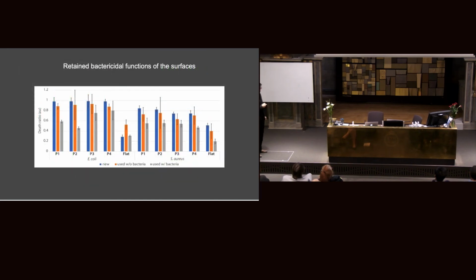After these bactericidal tests, we also examined the retained functions of the surfaces. This was done by comparing a newly fabricated surface with a used surface, where we put the surface into the bacterial solution, took it out, washed the bacteria off, and used it again. Used with bacteria means we take the surface, incubate it with bacteria, take it out, and put it back into a new batch of bacteria.